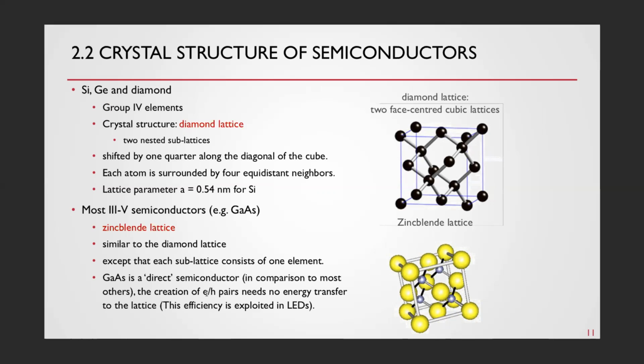It's because the energy levels they operate in are, of course, different, and hence, if you create an electron-hole pair, you have to transfer a small momentum to the lattice, and that gives you directional dependent effects, because the dispersion relation of an electron and a hole is first of all different in such a lattice, and it's also dependent on the direction.